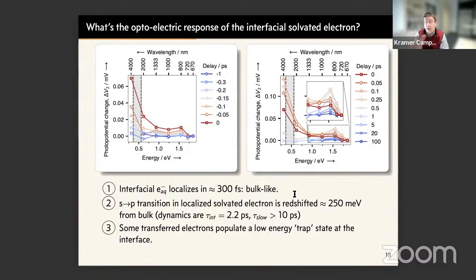Okay, so this is the qualitative sense of the data, but you might say, well, what does this mean? Well, we think this is now consistent with a scenario in which this interfacial solvated electron, the delocalized species, localizes on a time scale of, say, 300 femtoseconds. That's the time scale in which you lose this intensity at long wavelengths.